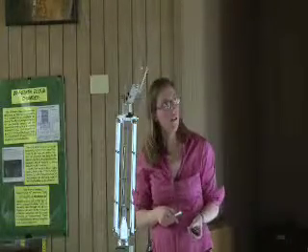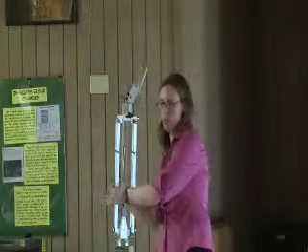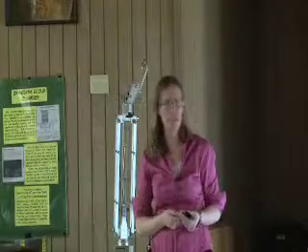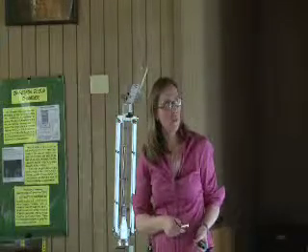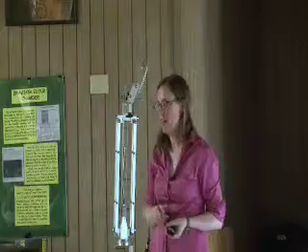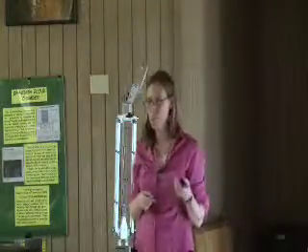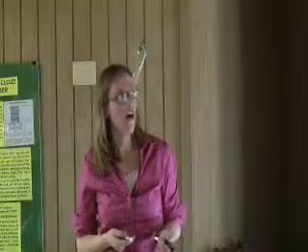If you apply a little bit of a magnetic field in this direction here while you apply the reversal field, then the whole bar magnet reverses from this direction to this direction as a whole. It still reverses a little bit quicker at the ends, but it reverses most of the way as a unit. And the reversal process is mostly finished in less than a nanosecond in this case. So techniques like this let us really see and get insight into what's happening on very fast timescales. And we can construct movies of what's going on.